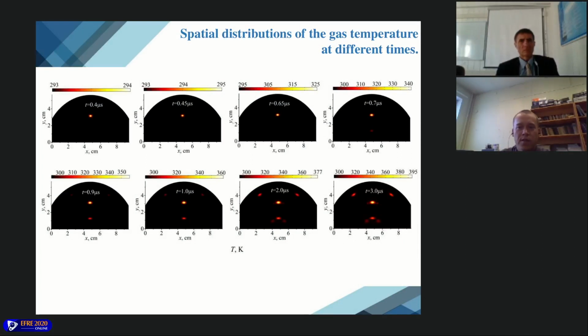It can be seen that after the formation of the first and second plasmoids, gradual heating is observed. In this case, the maximum temperature in the active phase of the discharge is observed by the time instant of 3 microseconds in the first plasmoid at the main focus of the system, and is 395 kelvins. In the second plasmoid, the gas temperature reaches 338 kelvins. In the 2 upper plasmoids, the gas temperature reaches 330 kelvins.